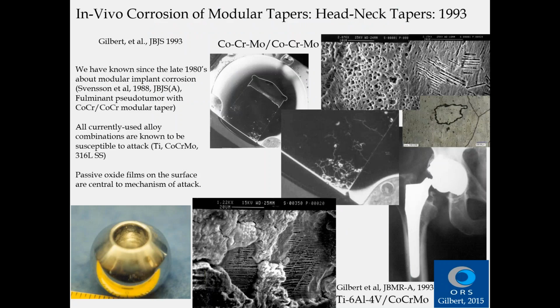Why are they important? Well, in corrosion in vivo, and I've shown this slide I think now for many years, we've known about the nature of corrosion of these medical alloys going back to the late 1980s, when in 1988, Svensson et al. showed pseudotumors forming from a cobalt-chromium modular taper junction. We also know that all of the currently used combinations of alloys are susceptible to this concept of mechanically assisted corrosion. The titanium, cobalt, and stainless steel-based alloys all have this oxide film, and as a result, they are susceptible to the disruption and subsequent repassivation reactions that can go on.